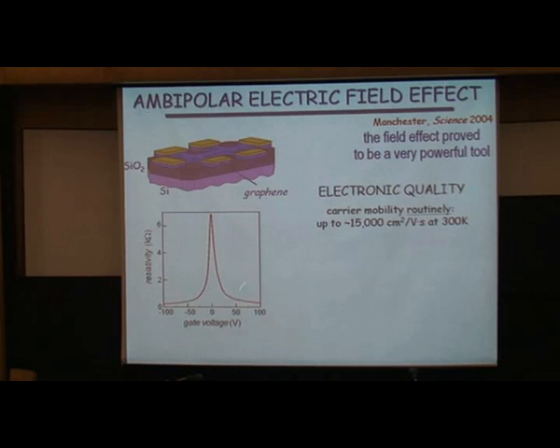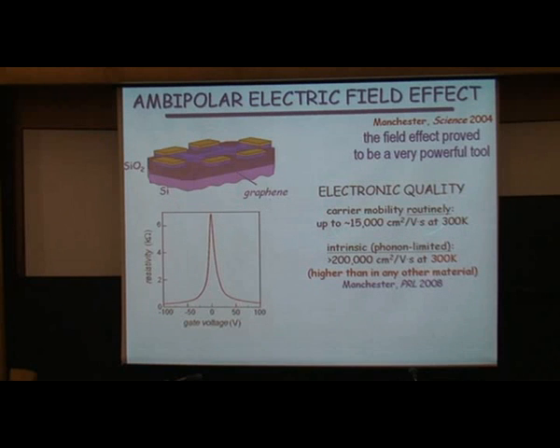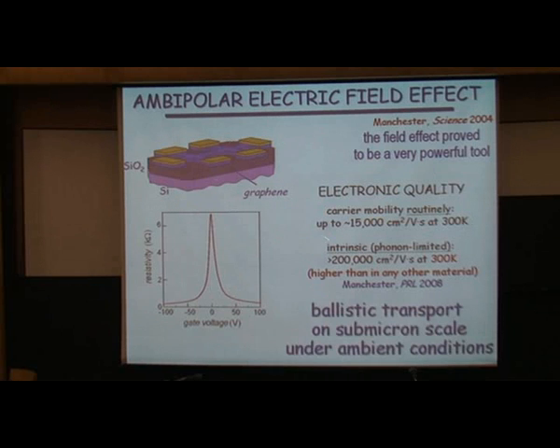In the very first work we found that electrons, actually, I don't want to give you such numbers like electron mobility and explain for those who do not know. So let me translate mobility directly into how far electrons go. Essentially, in this atomically thin sheet, which lies on a rough surface covered with all sorts of adsorbates, electrons shoot thousands and thousands of interatomic distances without scattering. Somehow these electrons are protected from external weather, so they can move without much hindrance over very long distances. Initially it was sub-micron distances. We hope at room temperature it could be micron distances or even larger.